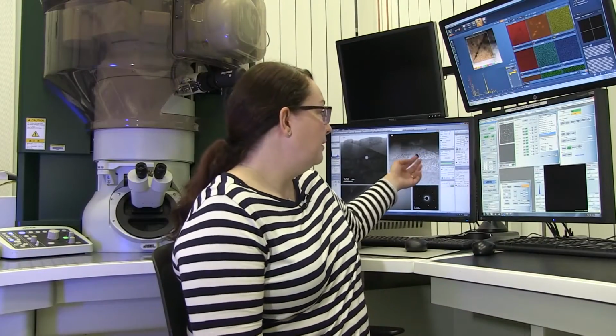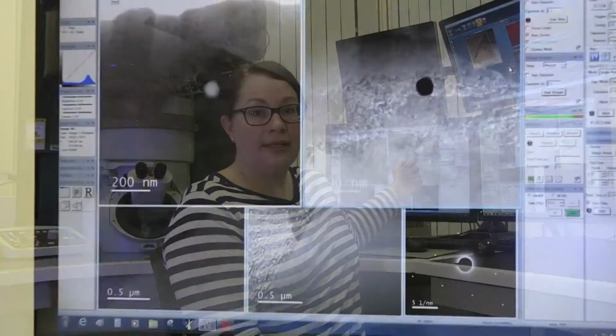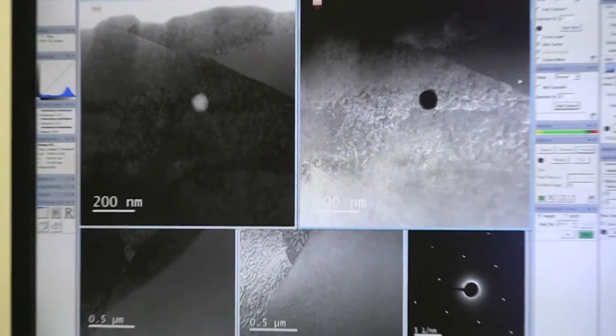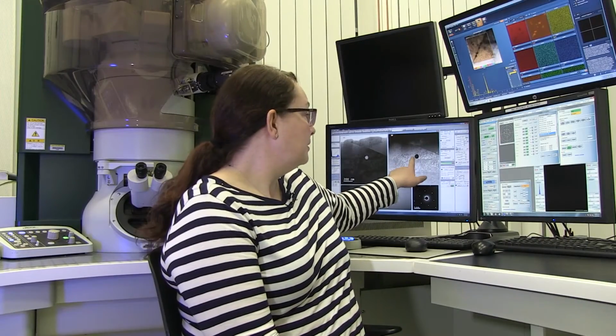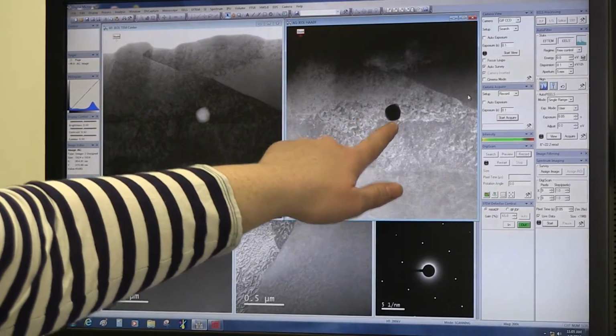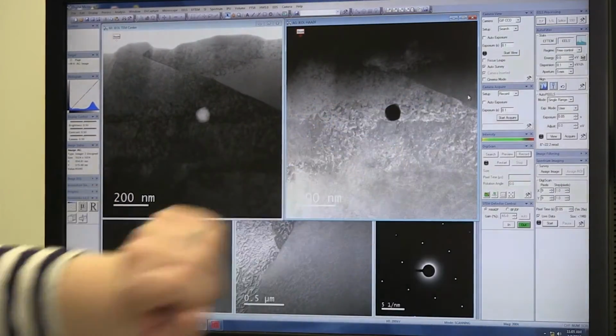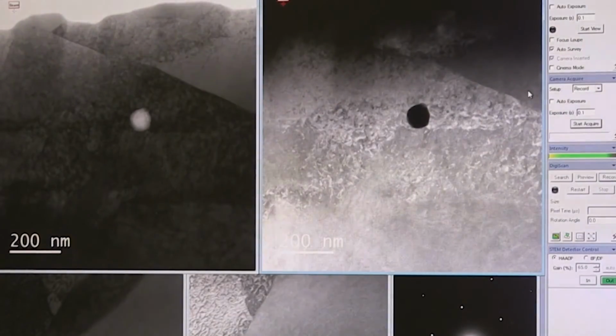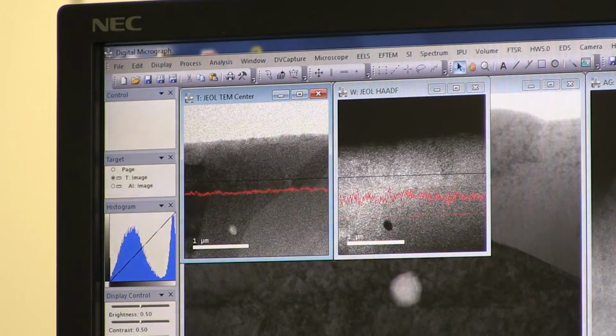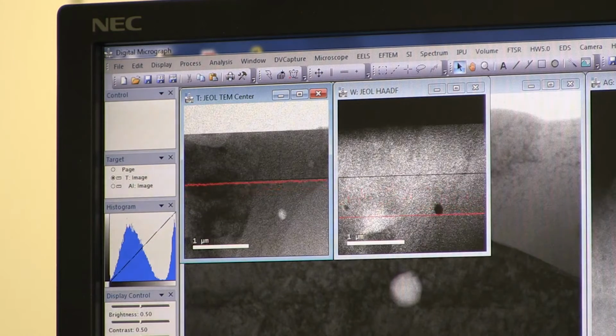So here's an example of a weld that we made in our fiber laser welding booth in the other building. There's a couple things that you can see here. One is that there's a pore in this sample that's about 70 nanometers in diameter. It's very small. You can't resolve something that small with your eye, but it can still actually have an effect on the mechanical properties. Cracks can form around pores and then they will break the material.